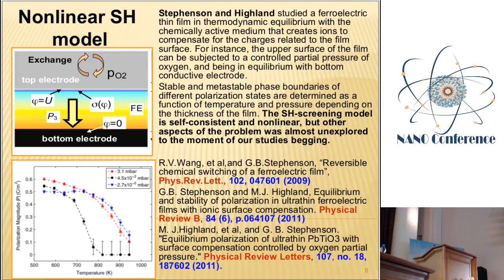The third case, which is important to my talk, is the case of ionic adsorption, the so-called Stephenson and Highland model. They made an experiment, and only then did they think about the theory. The experiment was very simple. They took a monodomain film with a remote tip electrode, and the distance between the film and the tip electrode was exposed to external oxygen pressure. They could change this pressure. And as a result, they found that the ferroelectric polarization critically depends on the pressure. At high pressure, the polarization is conserved, and at low pressure, the polarization disappears.